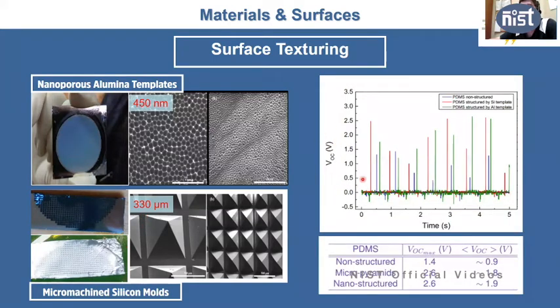This is just an example. So the output voltage that you get as a function of time for different structures. So for PDMS, simple PDMS films that are flat, with the silicon template that has micrometer features, and the aluminum template that has nanometer features. What you get is typically a 2 times increase in the output power just by changing the surface of your material, of your triboelectric material. And interestingly, the output voltage that you gain does not relate a lot with the size of your feature. So there is a minimum size that you need to get the maximum output increase available.